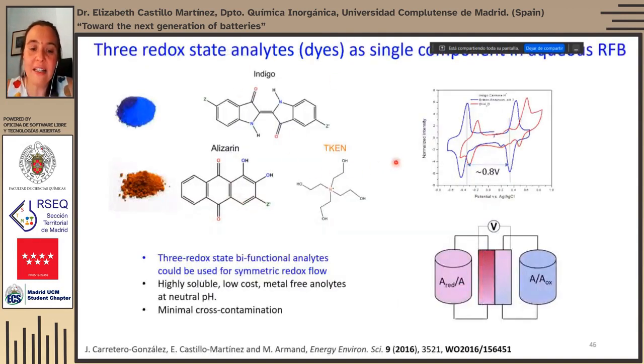Myself, I was involved in developing symmetric redox flow aqueous batteries, in which we were using dyes, which we functionalized to get a species that could be both oxidized and reduced, and therefore could be used again in a symmetric battery, with all the advantages that I've already discussed in terms of minimizing the issues with cross-contamination through the membrane. Although these materials seem to perform quite well and we reach solubilities of up to 2 mol in some cases, there are still some issues related to how the solubility changes when you go to the oxidized or to the reduced state.